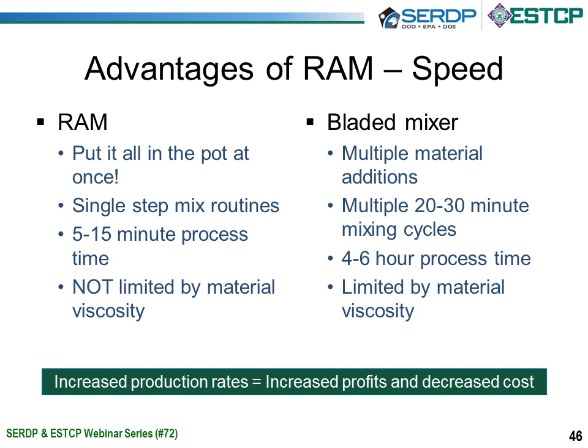So Eric described in the introduction to his presentation about the Faraday instabilities and how rapidly that mode of mixing converts the material into a very homogeneously dispersed composite material. On the right-hand side of the screen are the bullet points for the bladed mixer. Normally, for the bladed mixer, you make multiple material additions. Usually, a quarter of the solids or less is added to the bowl at a time. The blades are turned on for 10 to 20 to maybe 30-minute mixing cycles to fold the material in, and this process can take 4 to 6 hours, and it's limited by the material viscosity.